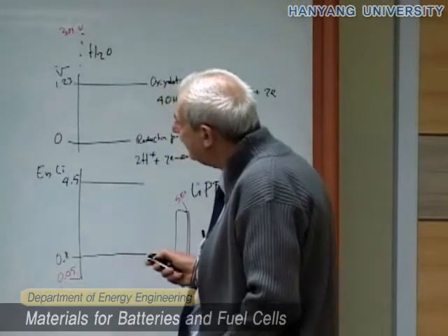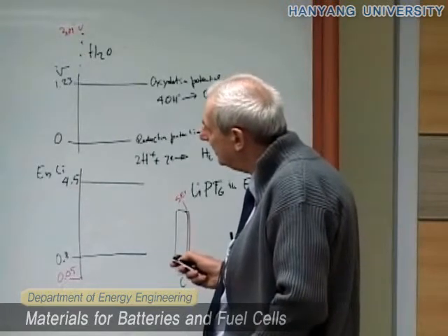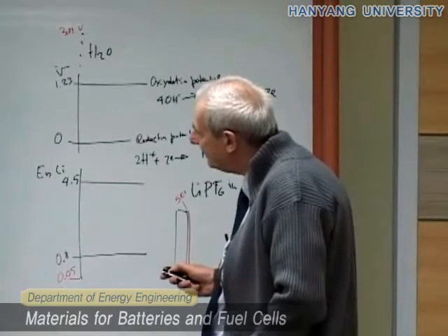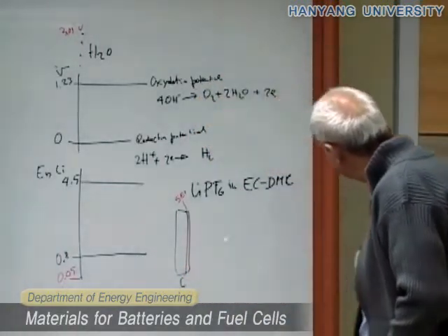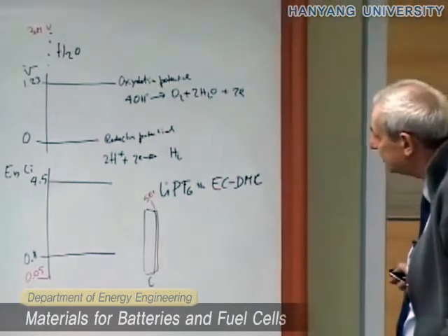Okay, the organic layer is formed by compounds such as lithium alkyl carbonate, this one, and lithium alkoxide, this one, both deriving from the reduction of EC. Remember, the EC is one component of our solvent.